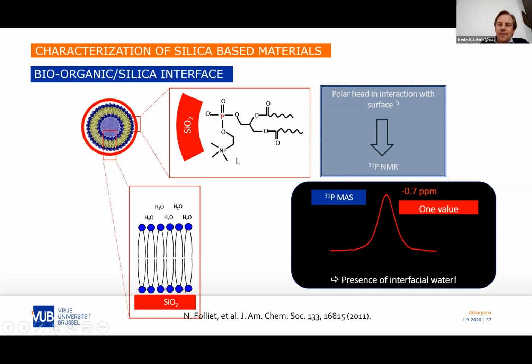And if you see here in the structure, I'll make an enlargement here instead, where you have the silicon, which is interacting with our polar heads, which is in blue. You have also the double layer, which is the other side, but there you don't have silica. There you have water. So in fact, what happens is that you have then two environments and not one, and the experiment shows only one.